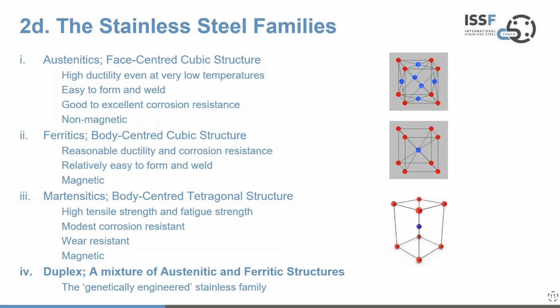The ferritics, by contrast, have a body-centered cubic structure. So rather than atoms at the center of each face of the cube, there's just one in the center of each cube, as well as the atoms around the corners. And here you get reasonable ductility and reasonable corrosion resistance. So some sacrificing of the corrosion resistance, but again, these are still easy to form and weld, and this is a magnetic family of stainless grades.